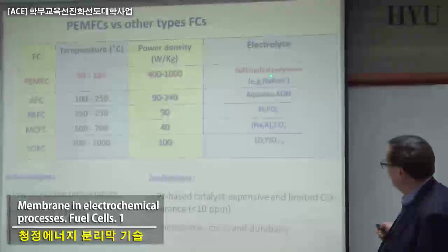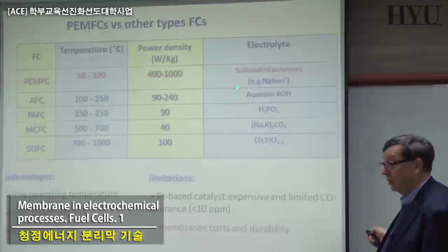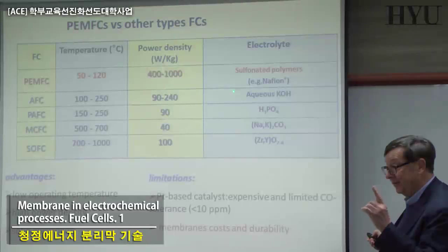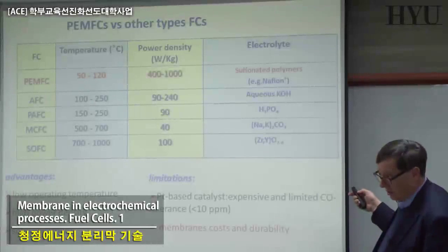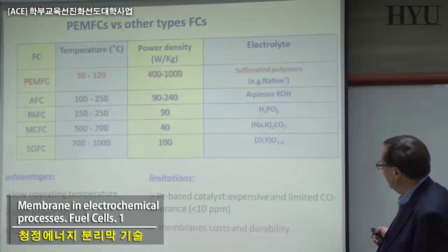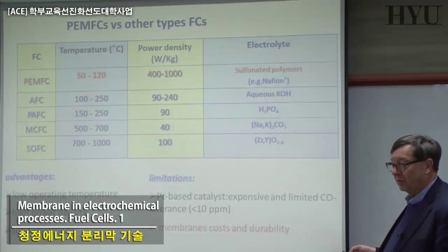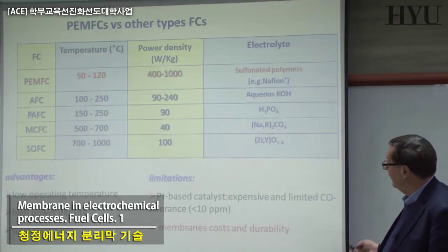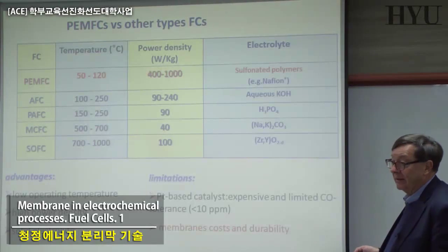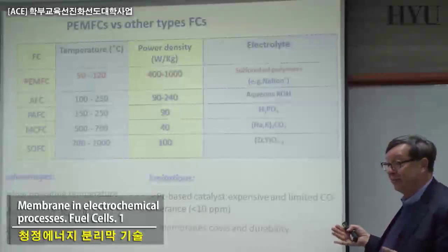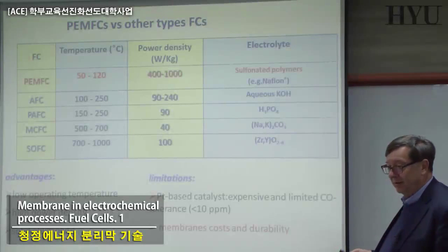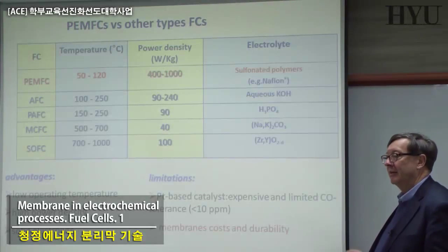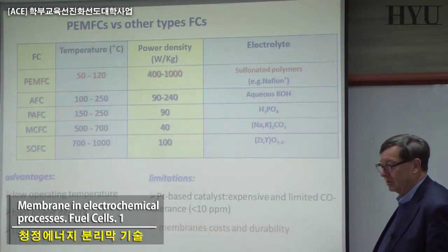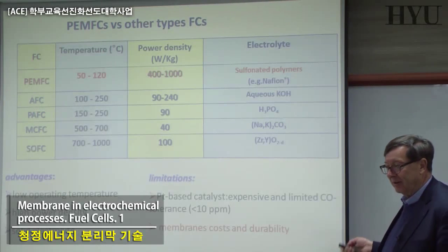The core of the system is related to the material for forming your ion exchange membrane, selective, able to transfer only this H plus, the H3O plus that we saw before. You see there's a name, Nafion, because today most of the real systems in real life use only one membrane all around the world, and that is a problem. If we don't have at least 3, 4, 5 different membranes produced in different countries, etc., there will never be a real utilization on a large scale, because if there's no competition, these kinds of things don't work.